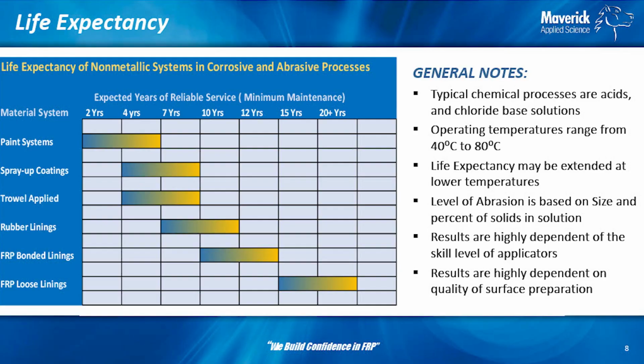So this is something that I put together that's a little bit different, that I haven't done before. We've talked about these different material systems, and this is based on our experience. This is what we see based on typical manufacturing practices and typical operation. All those things play a part in service life. Operating conditions of these are typically from 40 degrees C to 80 degrees C. If the temperatures are lower, you're going to extend the life because temperature doesn't play as much of a part.